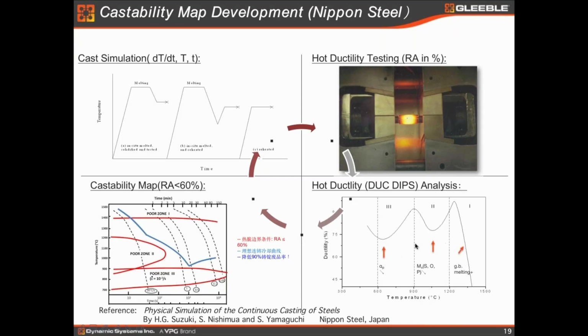Okay, and this one is very specific to steel. What they do at the Nippon Steel, it's called continuous cast steel. So this is one of the examples of their ductility curve at different temperatures at a certain specific strain rate and holding temperature. So you see there are 3 low ductility regions, what we call 1, 2, 3. And if you see the low ductility, you want to know why. You only know the origin of the low ductility, then you can improve it.